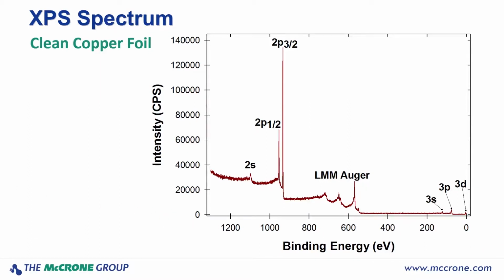So why is photoelectron spectroscopy surface sensitive? Well, the photoelectrons produced in this process have kinetic energies of, say, tens up to around 1,000 eV. And the inelastic mean free path of electrons with those low energies in solid materials is typically only a few nanometers. So any photoelectrons that are produced deeper into a sample cannot escape the sample without undergoing scattering.